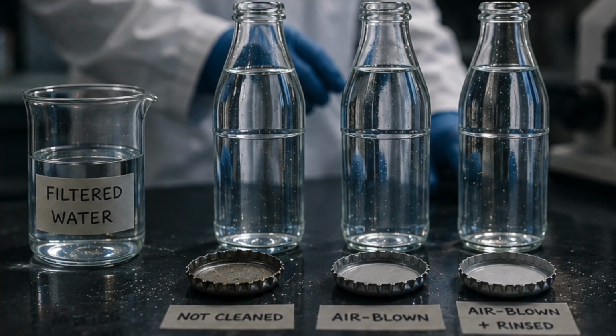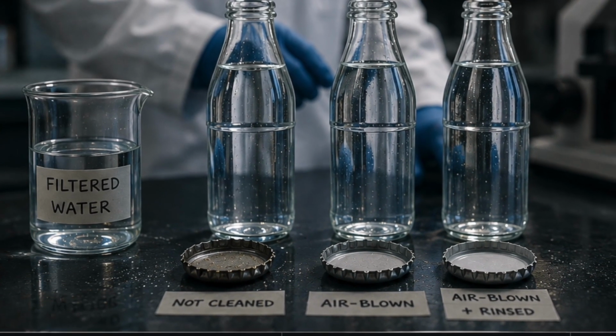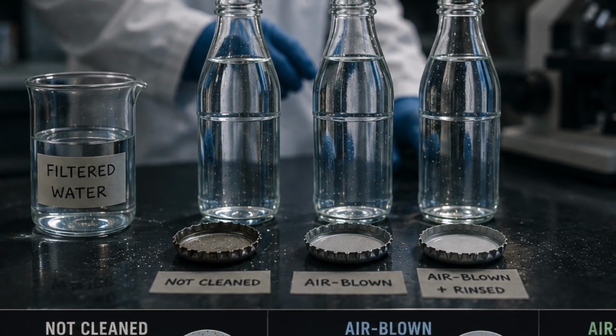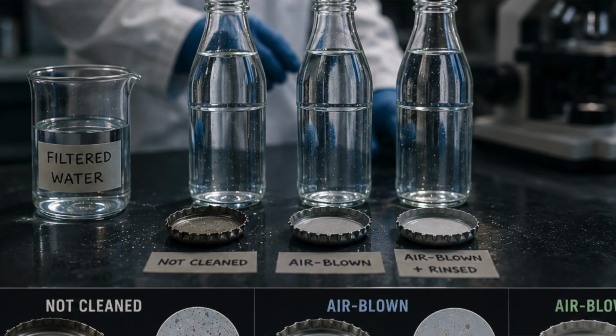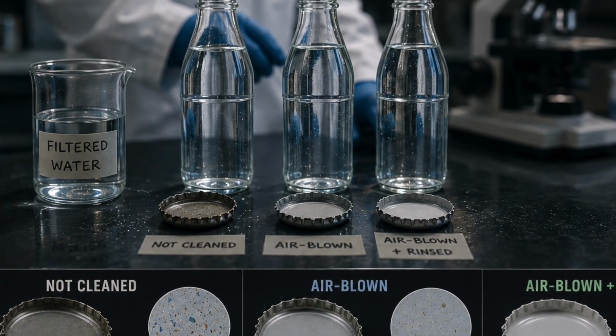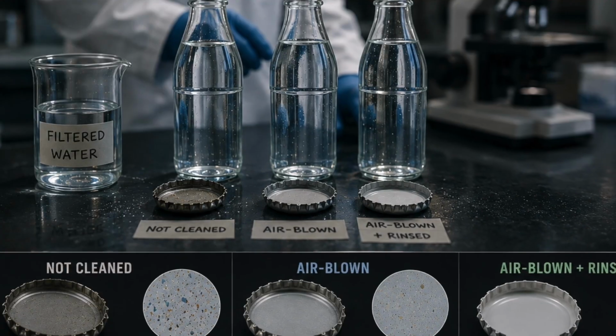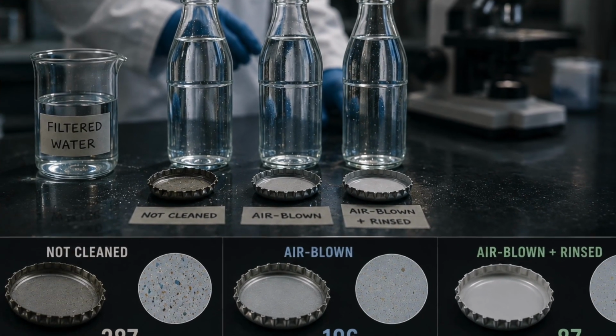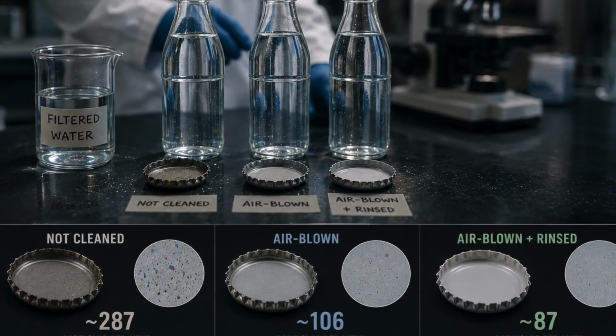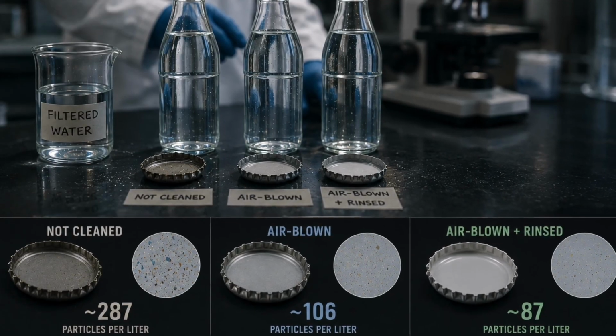To test this, the lab did controlled experiments. They filled perfectly clean glass bottles with filtered water, then sealed them with caps that were not cleaned, air-blown, or rinsed. With uncleaned caps, they found around 287 particles per liter in the water. After just blowing air on the cap, that dropped to 106 particles per liter. With blowing plus rinsing, it fell further to about 87 per liter. So the contamination followed the cap, not the glass.